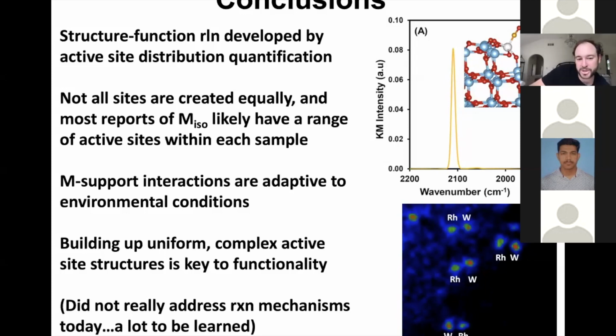If you look in the literature, most reports of these single atom catalysts or isolated metal atoms likely have a range of different environments of the metal species in a given sample. And you can tell this just by looking at the CO infrared and the inhomogeneous broadening that you would expect. Next is that these metal-support interactions are adaptive to environmental conditions. We saw that the coordination environment changed just by changing how much hydrogen or oxygen you put in the atmosphere. And further, that we can really begin to build up uniform and complex structures, and that this is going to be the key to approaching the functionality that, for example, organometallic catalysts have.